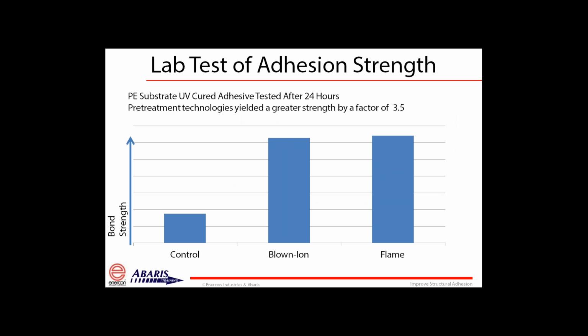One of the other tests that we've run is we've looked at bond strength. And this happened to be on a polyethylene surface, which we used a UV cured adhesive. We ran these tests after 24 hours. So we had a control component of polyethylene that was not treated, and then blown ion and flame treated systems as well. And what we saw is a factor 3.5 times greater of bond strength on that polyethylene with that UV cured adhesive. So a pretty amazing change on bond strength with that technology.